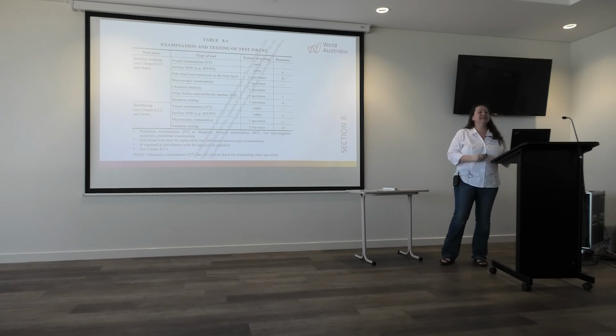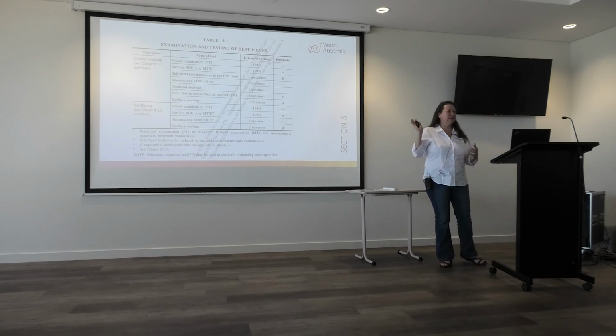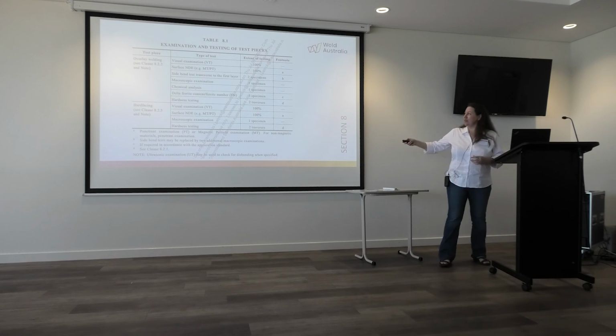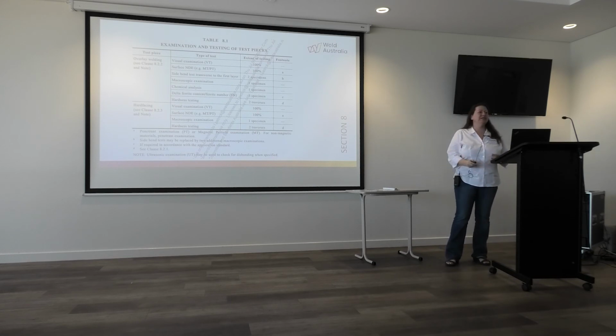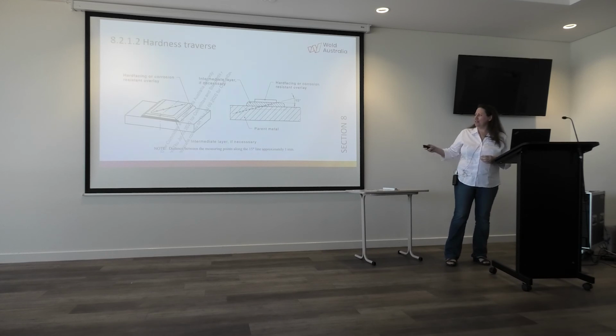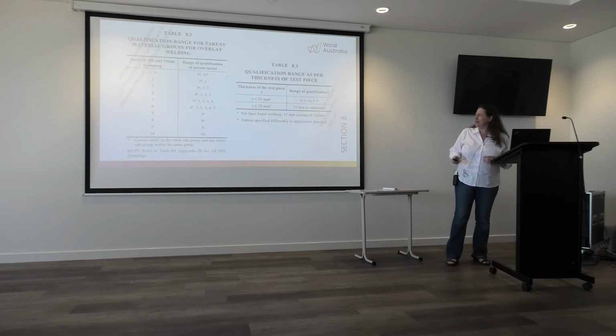And what I want to get to is that a table's been added, and this is out of ISO 15614 Part 7, so that you now know if you have an overlay, what type of testing do you need to do? Because the previous chapter was very wordy without saying much. Now you've got a table. You see, I can exactly test this. And if you do hardness testing for hard facing, you know you need your top hardness. For others, you need this at a slant so that you know what's happening in your heat affected zone, fusion layer weld. And then you've got a range of qualification for your parent material. So it's not just I weld one thing with a build-up and what do I do now?